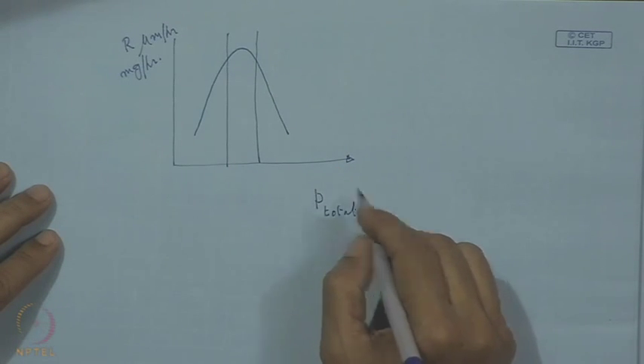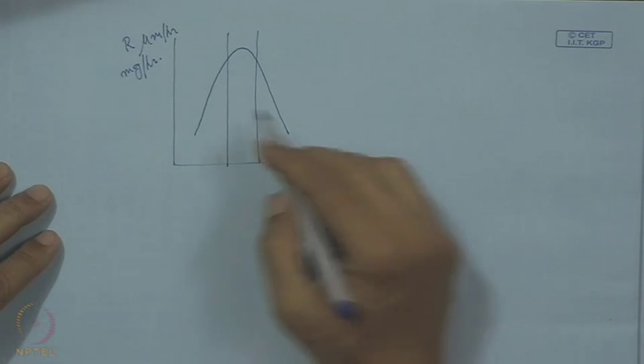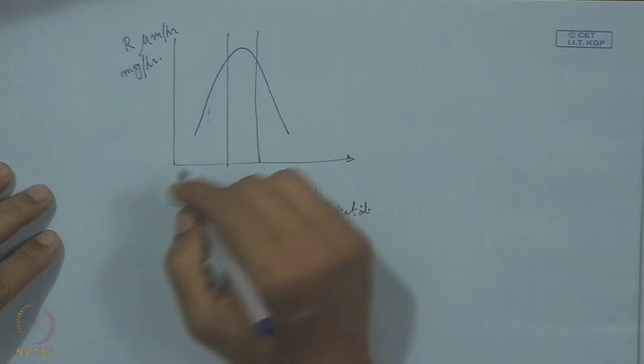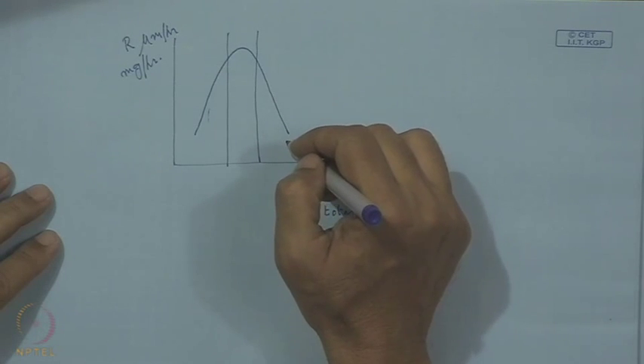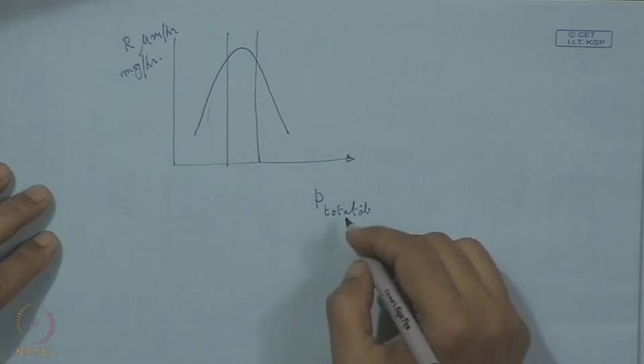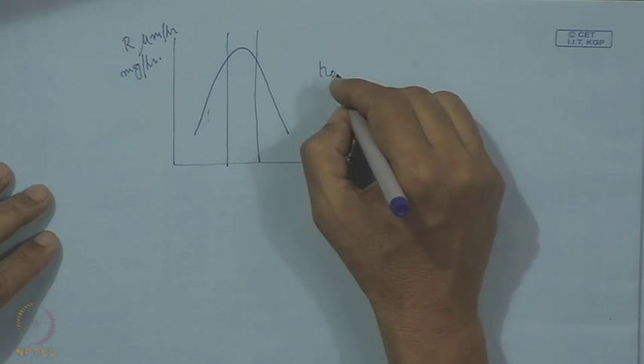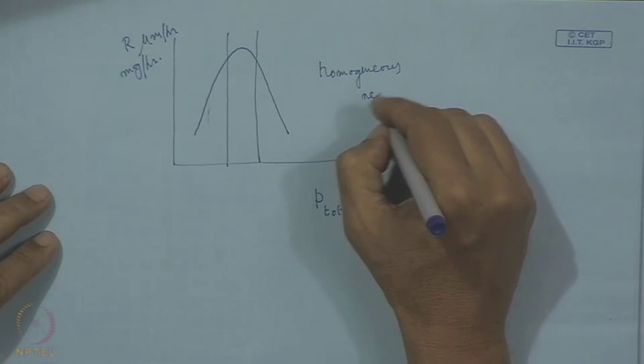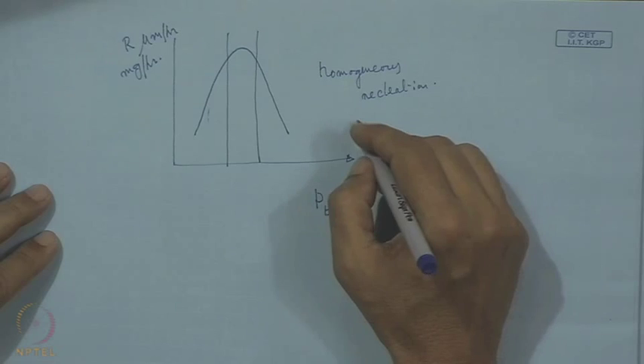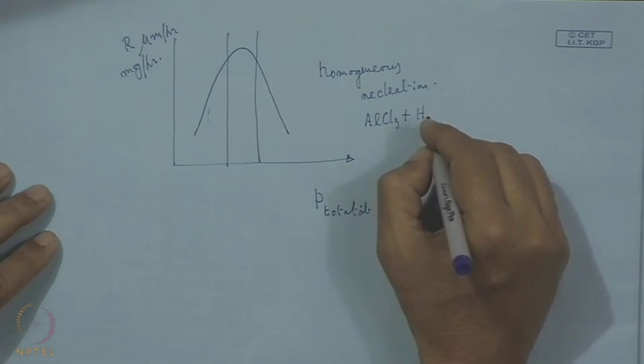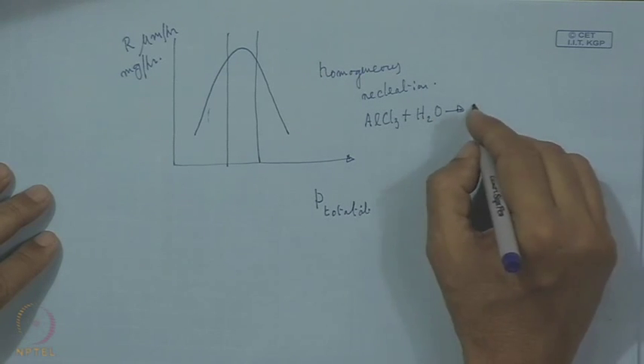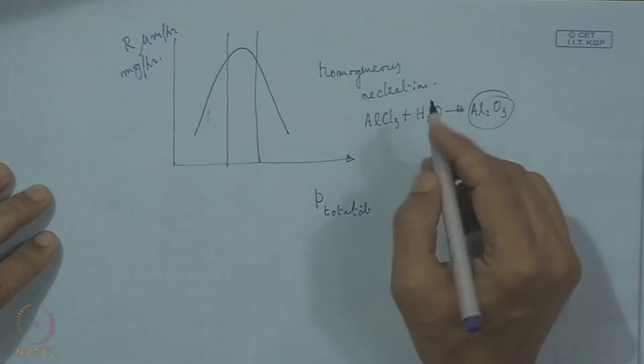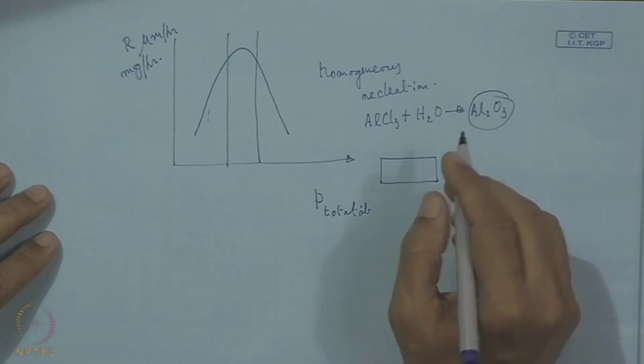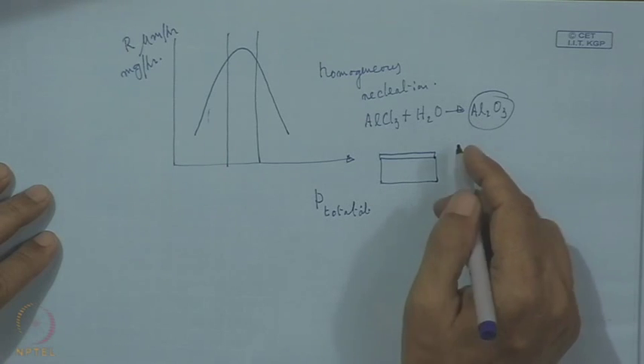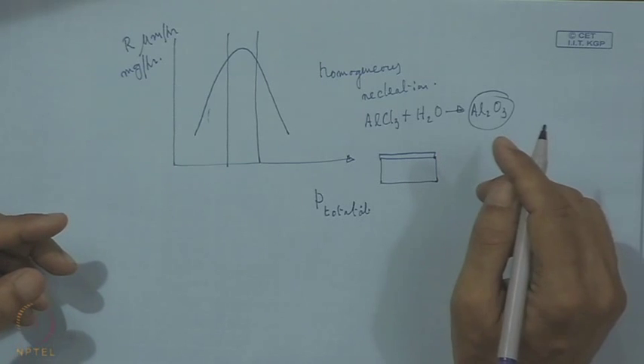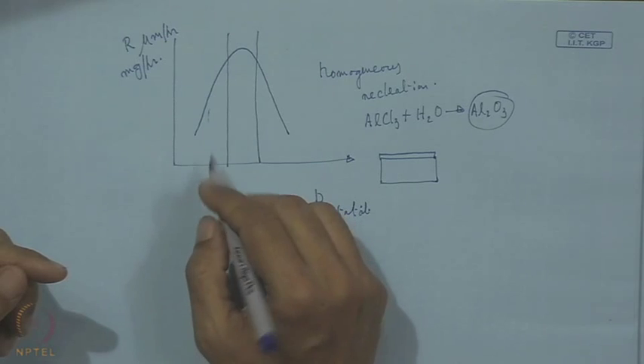If we are on the higher side, we can see the growth rate is falling drastically, and even with a low total pressure, the growth rate is also not adequate. Now, when we are on the higher side, with this high total pressure, we can have homogeneous nucleation. Homogeneous nucleation means this reaction is occurring in the gas phase. So, AlCl3 plus H2O, and if we have a very high pressure, then this Al2O3 may form in the gas phase, but ideally it is supposed to form, condense and synthesize on this carbide substrate, but this does not happen. So, the growth rate is obviously falling.